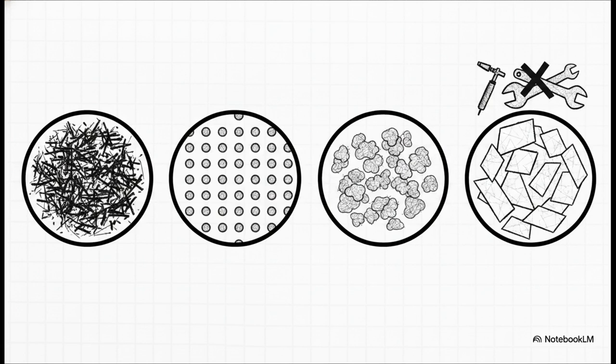But look at the last one on this list, white cast iron. The carbon here exists as super hard cementite, not graphite. While the first three can be repaired if you're really careful, white cast iron is practically unweldable. For that, you're generally looking at mechanical replacement, not an arc repair.